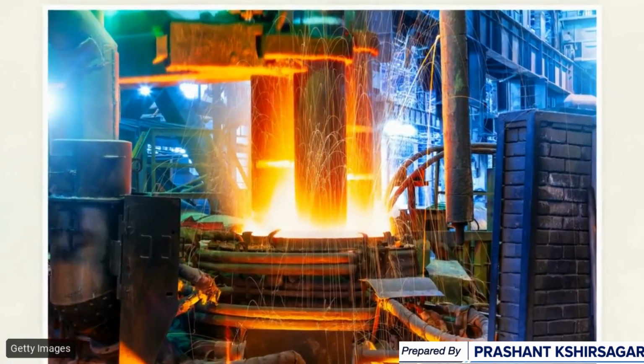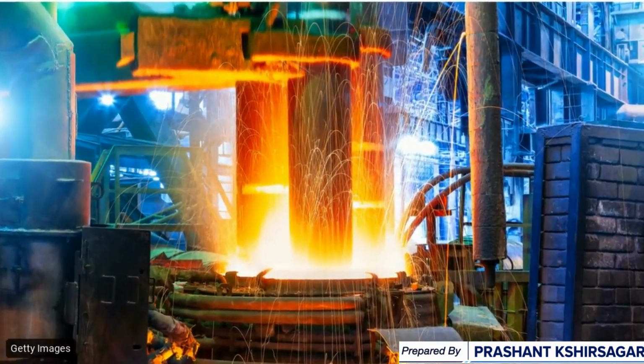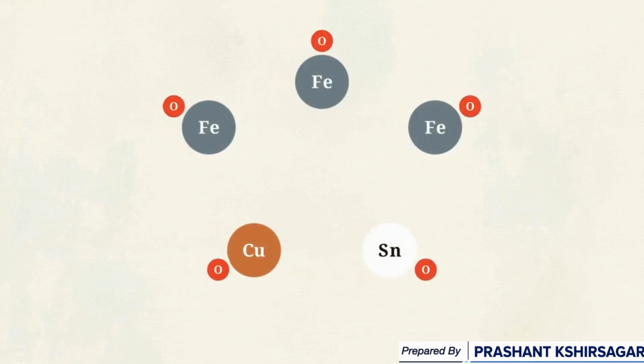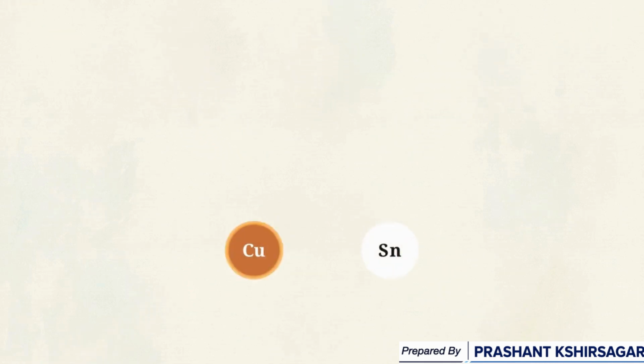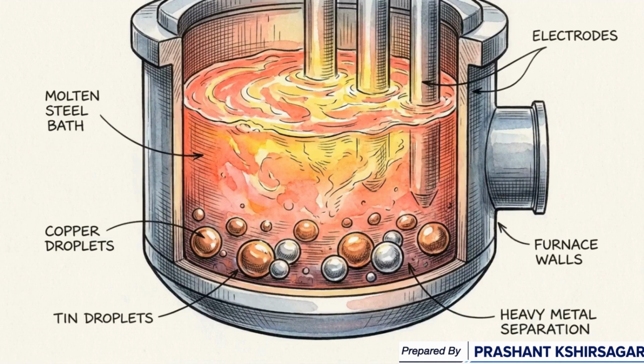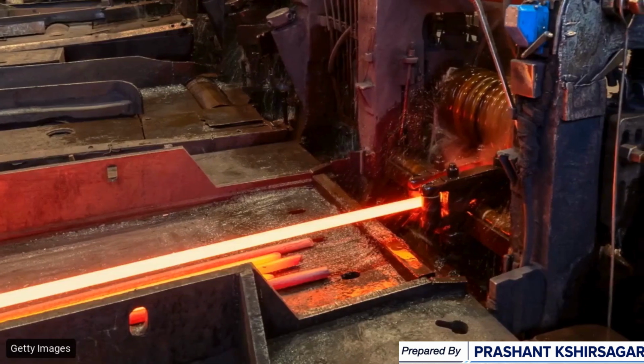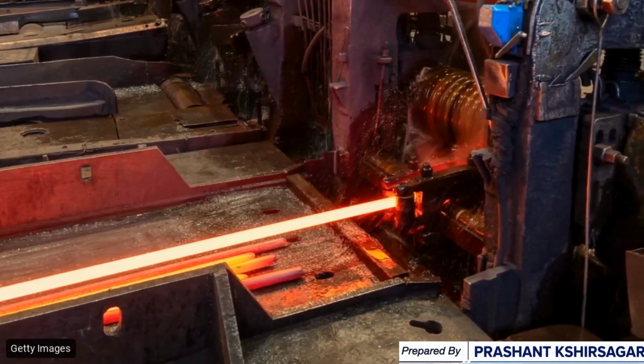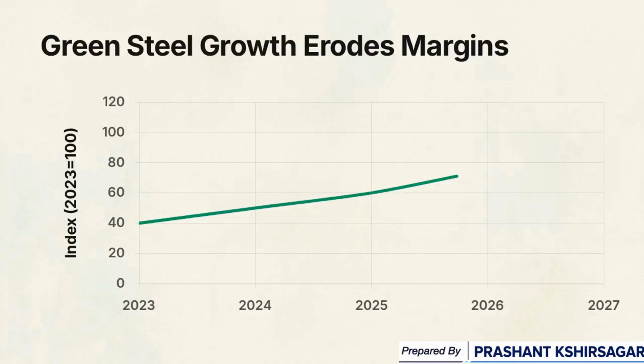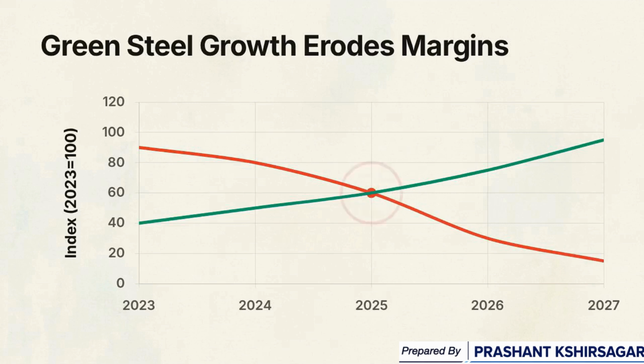These elements are metallurgically noble. When they enter the melt, their chemical affinity for oxygen is lower than iron. They completely resist standard oxidative refining. Because copper and tin cannot be burned away or slagged out in the furnace, they bypass traditional scrap gate checks and embed themselves into the final product, silently eroding the profit margin of the green steel transition.